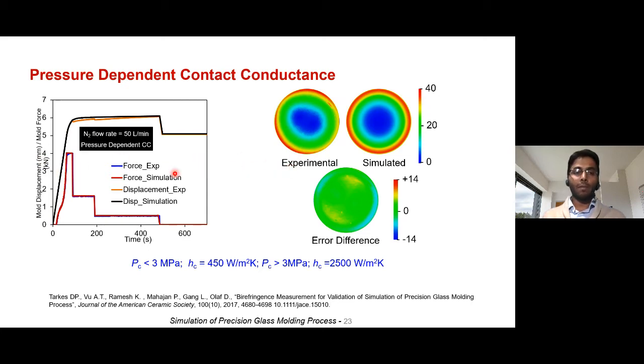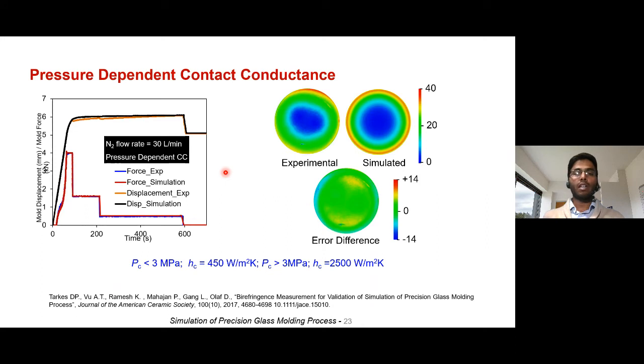All of these data we're able to match very precisely. This curve fitting was done for a flow rate of 50 liters per minute, and then we tried these values as a trial experiment for 30 liters per minute. It still worked very well. So based on this, we published some of these understandings in another paper in the same Journal of American Ceramic Society. One could refer to this paper for all the details.